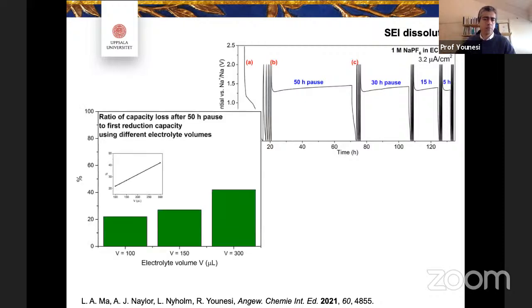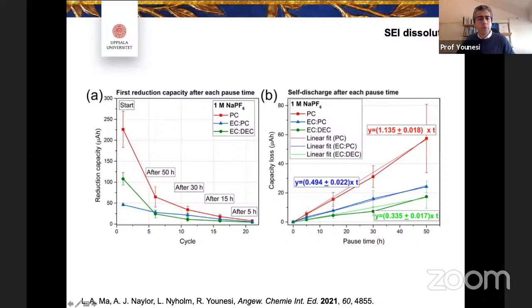And then we have shown that this SEI dissolution is very much dependent on the volume of the electrolyte, which is another indication that this effect that we observe is related to SEI dissolution. So following this type of method to understand SEI dissolution and aging in sodium-ion batteries, we have recently shown that for different electrolytes, these are just different carbonate-based electrolytes, PC, EC-PC, and EC:DEC, we can measure the amount of capacity loss over pause time. And you see, the longer the pause time is, the higher the capacity loss is. But if you look at the y-axis, we are talking about very small capacity loss, microamp-hours. This is very small, tiny capacity loss that we observe during pause, during relaxation, but this is definitely important to address and suppress if we are aiming for commercialization of sodium-ion batteries.